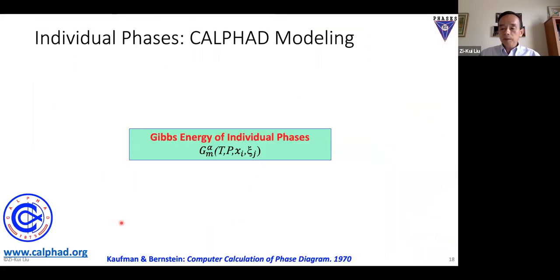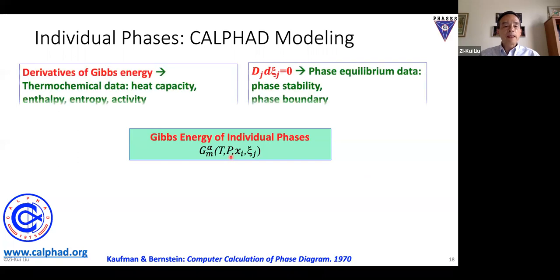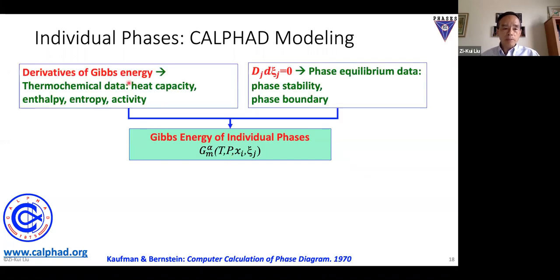So the process is that you can do the Gibbs energy of individual phases, since we are mostly working on temperature, pressure, composition instead of electrical materials. For oxides, for ferroelectrics, of course, you want to use electrical field and also strain instead of pressure. To do that, you need the derivatives - we'll talk about the first and second derivatives of the Gibbs energy, which give you heat capacity, entropy, and activities.